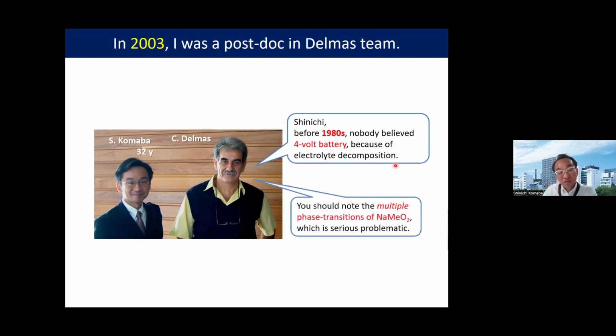Additionally, Dr. Delmas said to me that you should know the multiple phase transitions of layered sodium oxide, which is a different situation from lithium. Such phase transition is a very serious problem for practical use because during charge-discharge, there is a drastic lattice parameter change, then cracking and collapse of the active material.